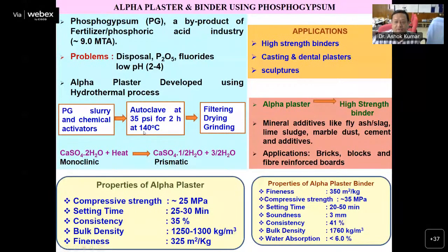So we have developed the high strength binder using this alpha plaster by adding some mineral additives like fly ash, slag, lime sludge, marble dust, etc. The major properties of these binders are high compressive strength, about 35 MPa, setting time between 20 to 50 minutes, and water adsorption of less than 6%. So this binder can be used for exterior as well as interior purposes.